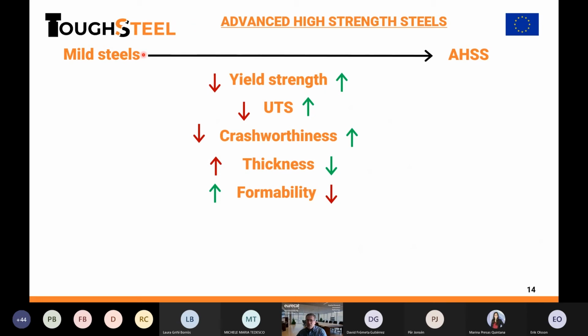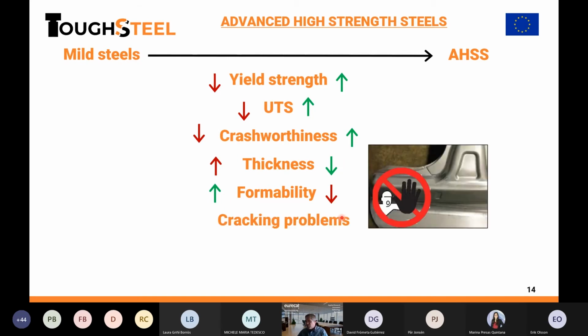Yes, this is the path from mild steels to high-strength steels. Definitely with high-strength steels, yield strength is higher, as are tensile strength and crashworthiness. We know that experimentally. This allows decreasing the sheet gauge, so the thickness is lower, then it's a lighter material, but formability is compromised. We know that because we have edge cracking problems in forming. We don't want that. This is one of the problems that hampers the definitive application of high grades of high-strength steels in many applications. The forming problems: you cannot afford one or two cracked parts in your serial production. This is absolutely not efficient.